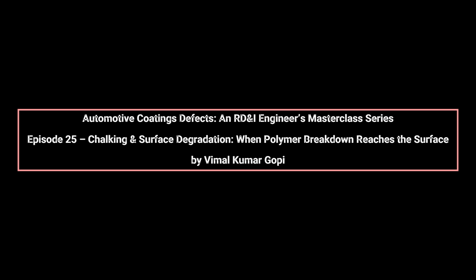Environmental conditions dictate chalking rate. High UV intensity, elevated temperatures, and low rainfall accelerate chalking because degraded material accumulates instead of being washed away. This is why chalking is more visible in hot, dry climates. In humid or rainy regions, degradation still occurs, but the chalk residue may be less obvious because it is periodically removed.